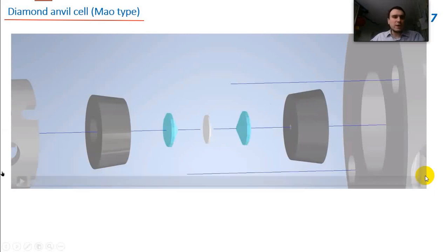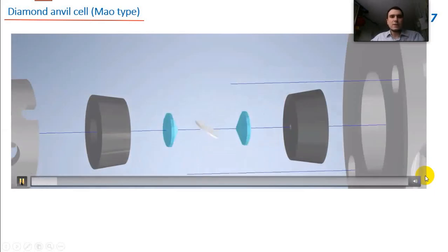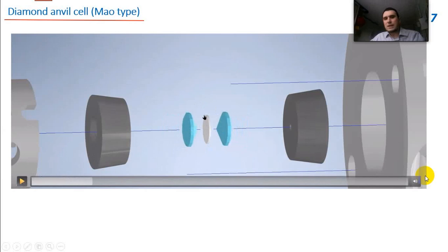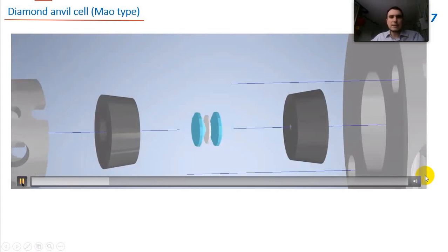It consists of several parts. Okay, let's assemble it together. The part in the middle is called a gasket. It's a metallic plate, typically rhenium, with a thickness of about 300 microns. After that, we press this metallic gasket with two diamond anvils. These are cone-shaped diamonds with a plain top, which is called the culet. The culet size is about 50 to 100 microns, and the diamonds press the gasket.